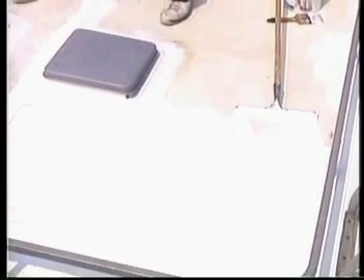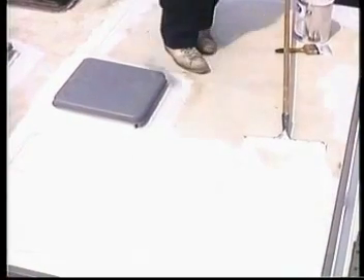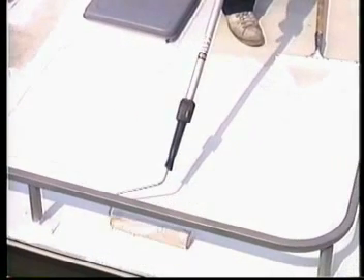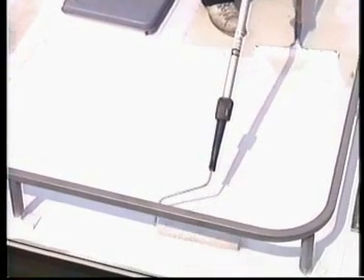If you're spreading liquid roof too thin, it will drag on the brush or roller and will either not self-level or require more than 10 minutes to level. If too thick, liquid roof offers little spreading resistance and the surface levels in about 1 minute. You have the right thickness when it's comfortable to spread with slow brush or roller strokes and takes 3 to 5 minutes to level.